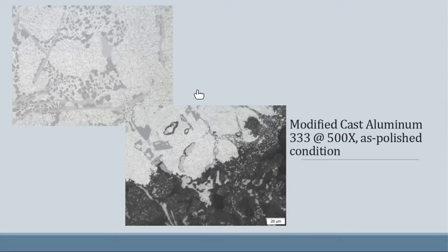Why did this fail? Well, they allowed it to come in contact with hydrochloric acid, at least a cleaning solution that has up to 9% hydrochloric. And what they did is they shut this valve off and allowed it to sit while they went to lunch. When they came back from lunch, it exploded. So this whole pump ended up blowing up on them.